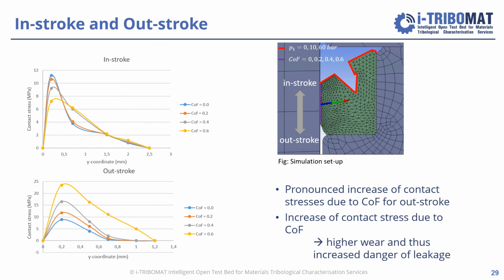There you see, for all coefficients of friction, the contact stress increases first to a maximum and then gradually decreases as you move on with the shaft. But this maximum increases pronouncedly as you increase the coefficient of friction, and thus also the decrease is smoother and takes a longer way until you reach zero contact stress.